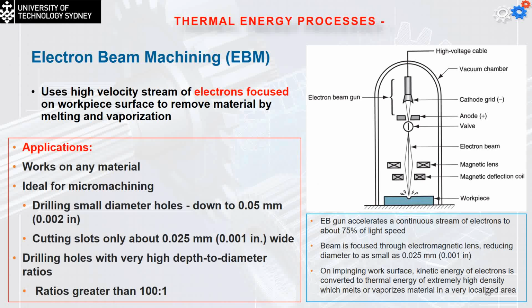This anode directs things. We're going to have the valve. The electron beam will be generated. We use the magnetic lens to direct the electrons, and we concentrate them in a very small area. Too much energy in a small area will cause the metal's temperature to increase and start to melt. So it uses a high velocity stream of electrons focused on the workpiece surface to remove the material by melting and vaporizing.